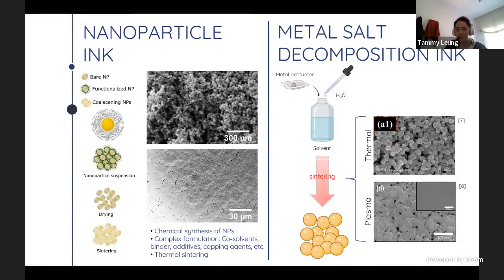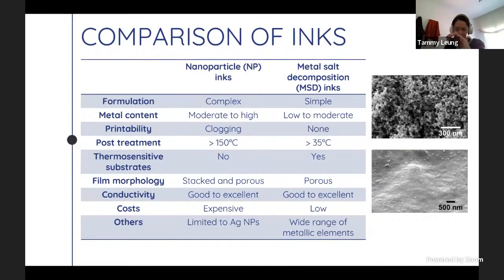On the contrary, a new type of ink that I want to introduce here is the metal salt decomposition inks, which is a simple formulation that requires just a metal precursor, water, and solvent. This simplified formulation helps to reduce the sintering temperature, but also allows for the introduction of novel sintering techniques, such as plasma, which again allows for a much smoother, uniform film, and allows also for the nanoparticles to combine or coalesce together. The table here shows a direct comparison of the advantages and disadvantages of each ink. So there seems to be a steady evolution where the complexity of the formulation is reduced while also being able to incorporate thermally sensitive substrates as this becomes more and more important in flexible electronics.